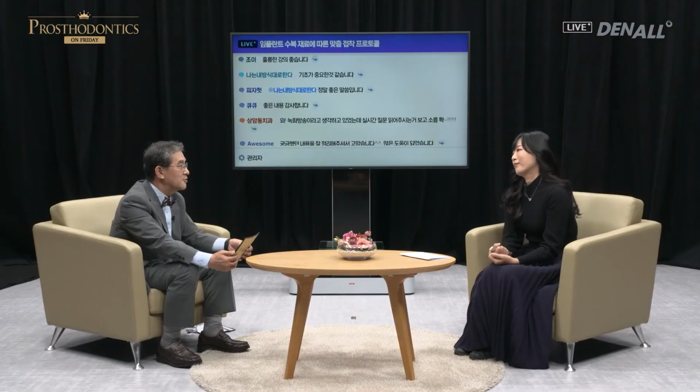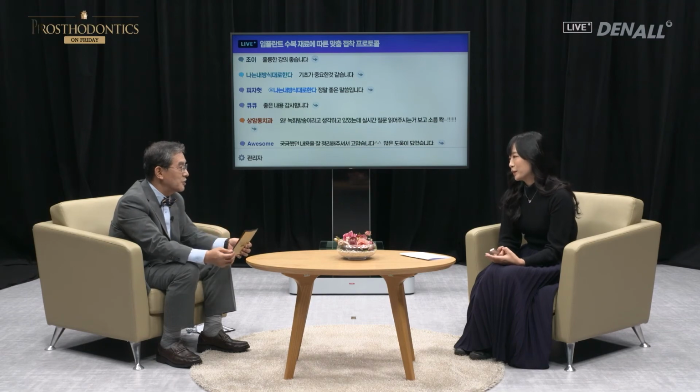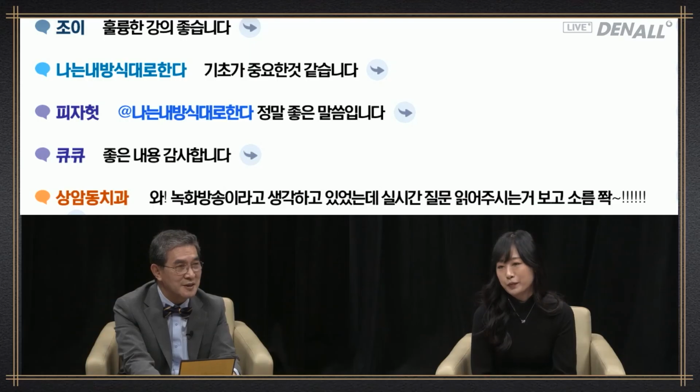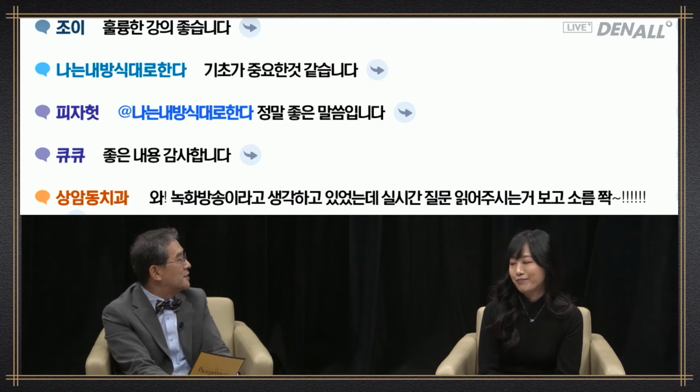In the case of light curing cement, use it on thin or highly transparent material like glass ceramic. In the case of dual curing cement, you can use it on zirconia or PFM restoration. In the case of self-curing cement, you can use it on PFM or gold, which has no light penetration. In other words, you need to use cement from a good vendor rather than worrying about the way. You need to increase the polymerization rate using the correct cement.